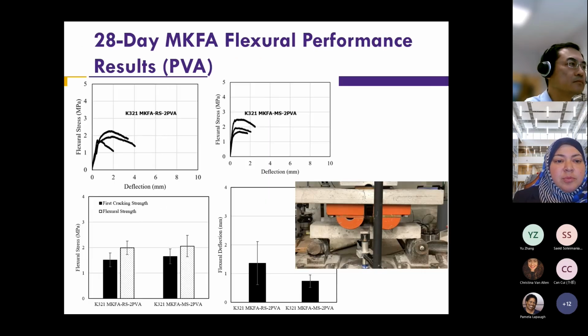This is the sad part, and we're still working on modifications, but when we tested the hybrid metakaolin fly ash combination, we were not able to get the pseudo strain hardening behavior that we were hoping for, so these mixes cannot be classified as ECCs.